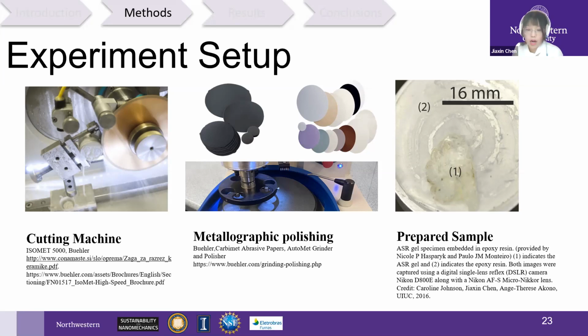After the final step of polishing, we used a small load scratch test to check the force profile on the surface. The last image shows our prepared ASR gel crystal specimen ready for the scratch test and indentation test. Number 1 is the ASR gel here, and number 2 is the epoxy resin. We can see a smooth and flat surface for our prepared sample.